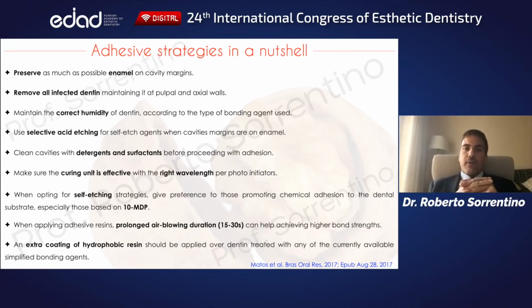Periodically check the power and wavelength of light curing units. If choosing self-etch techniques, always use MDP-containing primers. Vigorously blow the adhesives to completely spread them over the adhesive surface, creating a very thin and homogeneous bonding layer. And finally, apply an extra coating of resin to seal any possible porosity of the adhesive interface.